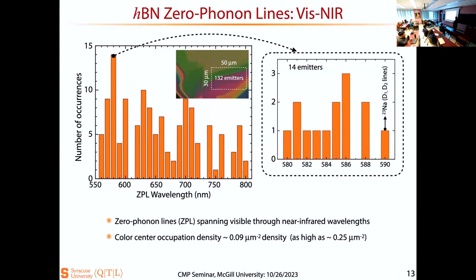One open question is, are these all different color centers? The answer is most likely no. Maybe this is one kind of color center, but because of the local strain, local inhomogeneity, their zero phonon line has started to shift. That could be possible. And I would be very, very surprised if it turns out they are hugely different color centers. If it turns out that these are really different kinds of quantum emitters, it's an advantage, but most likely it's not.